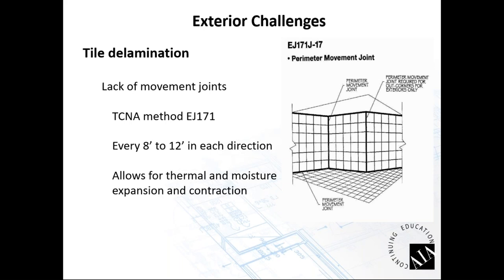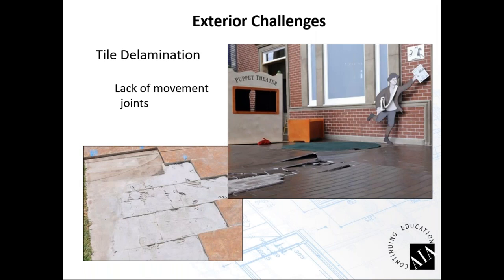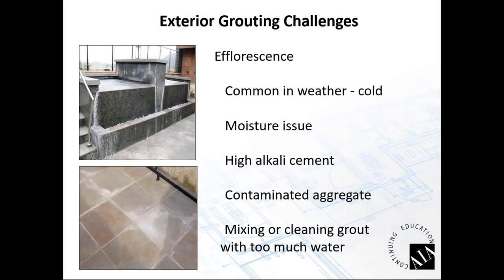And in the cases now, getting into the larger panel tiles, we saw where we talked earlier, up to 4x4 panels that can be directly bonded. In that case, we're not using grout. We're going in with a siliconized caulk around the perimeter of that panel so that the whole panel has an expansion or movement joint around it, rather than grouting it in with a hard grout. Things to take into consideration as you're going into the larger panel. Here's an actual application showing lack of movement joints: the tile buckling and coming off the substrate because movement joints weren't placed, and as the tile expanded because of heat, losing that entire floor.